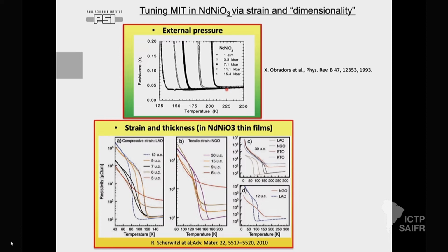So if you have the film grown on a different substrate, you will be able to induce the stress in the system via epitaxial strain. So if you have neodymium nickelate grown on the LAO substrate, then there is compressive strain of the bonds. You could see that for a relatively thick film of 12 unit cell, the transition temperature is already very low. It's 120 Kelvin. If it is a relatively thick film of 30 or 15 unit cell grown on NGO substrate, that will be tensile strain, you have the TC which is lower than in the single crystal, or the powder crystal form, but this is around 160. So there is a big difference between those three systems, right? And we have to understand why it's like that.